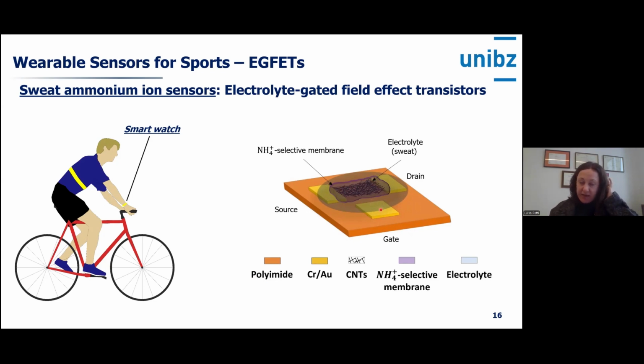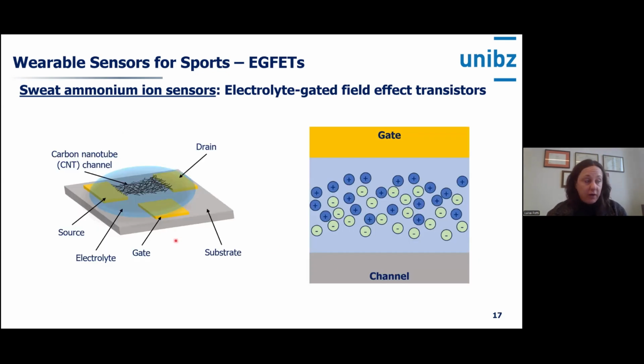In this case, those are microfabricated, so we are talking about evaporation and lithographic lift-off. So it's not a completely printed platform. The carbon nanotubes, the semiconducting layer we chose, are spray coated, so printed spray coated layers of single wall carbon nanotubes, a random network, what you see here, that basically connect the source and drain. Because the final application is testing everything in sweat, the electrolyte used is artificial sweat. To make this selective for ammonium ion sensing, we use an ion selective membrane for ammonium ion, an ionophore.